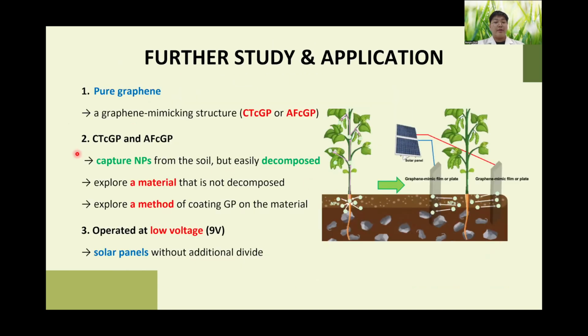Although the graphene film effectively captures the nanoplastics in the soil and prevents their penetration into crops, the agarose films were degraded due to soil moisture and the graphene powder was detached from the silicon tape as time passed. Therefore, exploring moisture-resistant, non-toxic flexible materials and developing a technique to coat them with graphene powder could enable long-term use, providing a sustainable solution without additional costs.